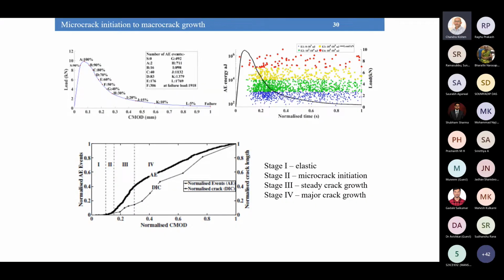So again, here in direct tension, we see that all events of all energy levels are formed. Basically it is happening after the peak load. In the case of direct tension, the way failure takes place is shown by this curve: normalized acoustic emission events and the crack length. So both are plotted here. The crack length is obtained from digital imaging. The acoustic emission events are micro cracking, captured through acoustic emission, and this is a normalized CMOD.